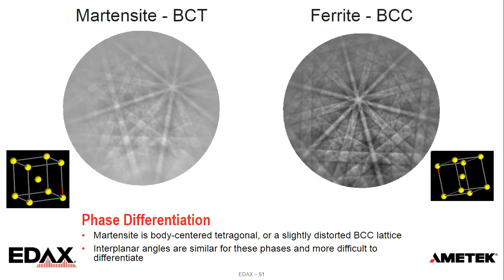And then this is one, we were saying we had a question that came in before the webinar started, to talk about this a little bit. This is a question that's been around for EBSD for a long time, of how do we differentiate something like martensite from ferrite? So martensite is body-centered tetragonal, and it's a slightly distorted BCC lattice, distorted from the temperature change and phase transition from austenite into martensite, of how that strain is retained in the unit cell. So basically what it means is that the cube is just slightly changed. And one of the things that's tricky is the slightly can depend on a lot of things. It's not always uniform in your alloy. It can vary with local carbon content. And so the interplanar angles between these phases are very similar. It can be more difficult to differentiate.